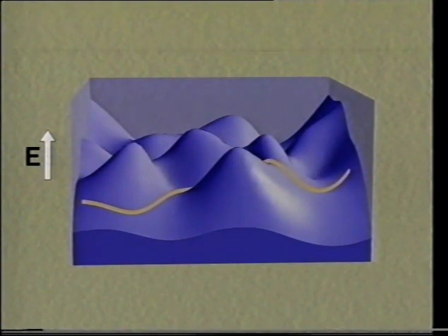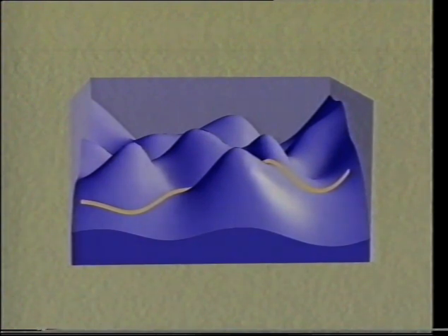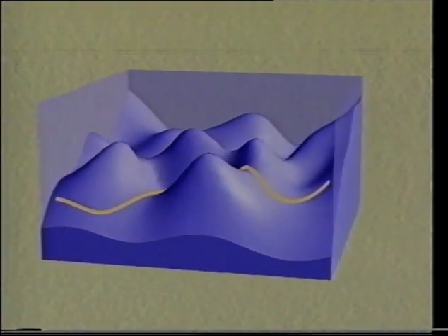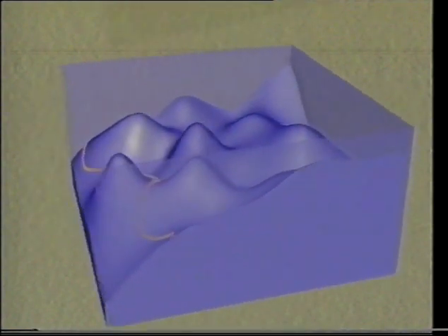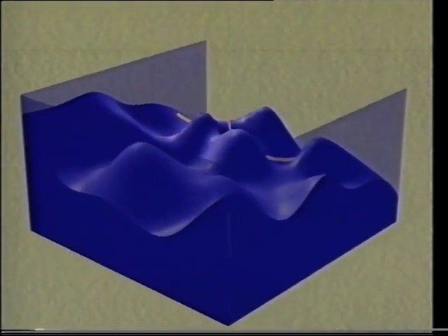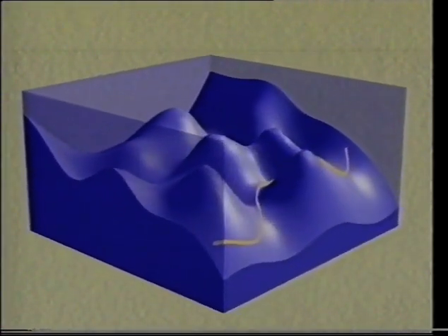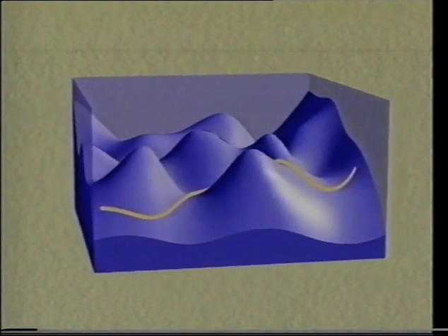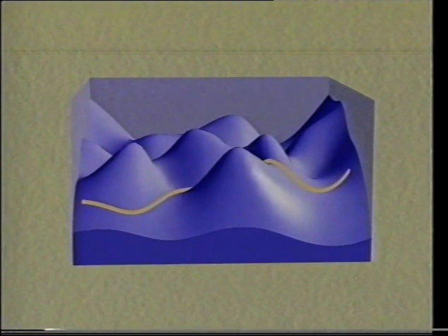However, if it does this, the dislocation gets longer, which costs energy, so the final shape adopted by the dislocation is a compromise, which minimizes the total energy, potential plus dislocation energy. This compromise takes the dislocation near to, rather than along, the valley floors. Now you can see that any large-scale movement of the dislocation will involve climbing out of the valleys. That is, it will require extra energy and stress to move the dislocation. We conclude then that due to the flexibility of a dislocation, other strain fields always act as obstacles, and this fact accounts for work hardening and precipitation hardening.